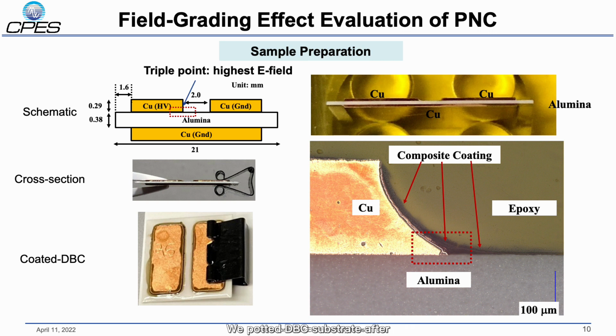We potted a DBC substrate after the PDIV test into epoxy, and then we used an auto polisher to polish down the sample to the triple point plane. Here shows a zoomed-in optical image under a microscope. Here is the copper, here is the alumina, and this is the putty material we used. It's the epoxy, and this dark region is our composite coating, and here is our triple point.